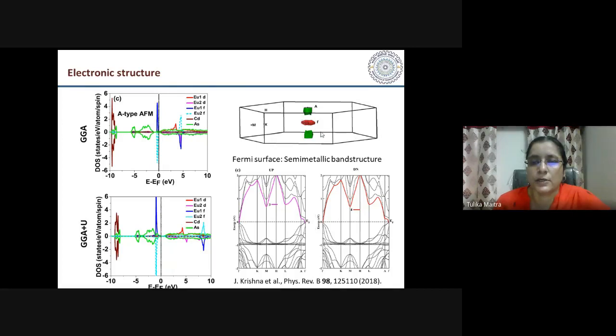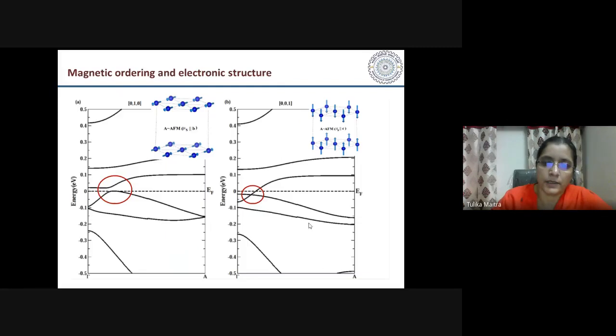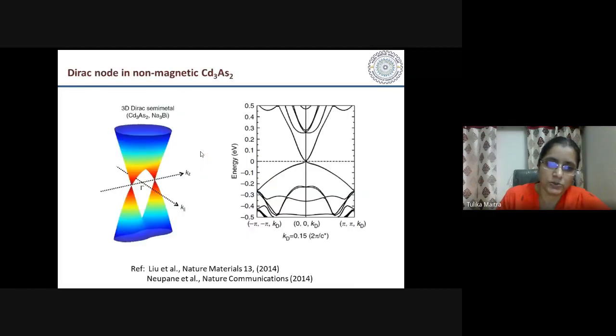This is the Fermi surface, and further one can see that there are these interesting points, this Weyl point just below the Fermi level when these spins are pointing along the C direction, and this is gapped when these spins are pointing along the B direction. Okay, so this is similar to the non-magnetic counterpart, which is Cd3As2, which hosts this Dirac semi-metallic state.